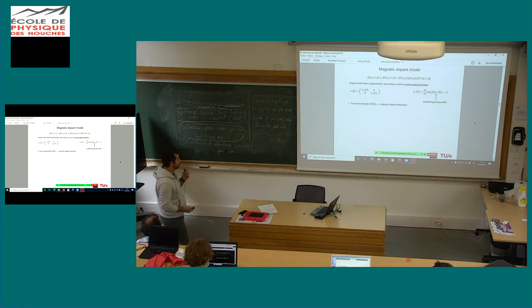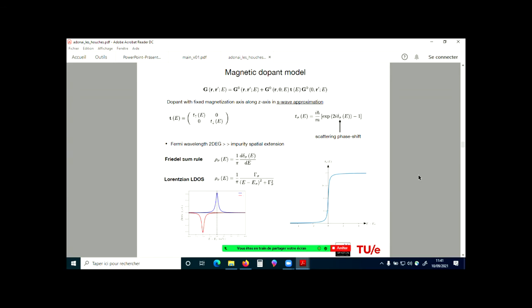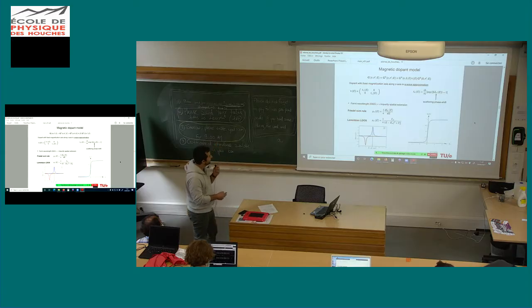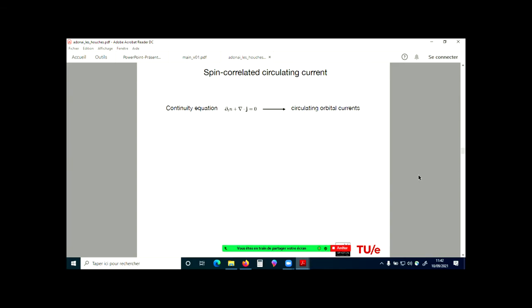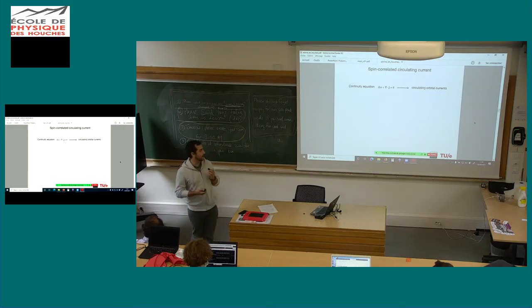I have this expression for the T-matrix in terms of the scattering phase shift. And this can actually be simplified in a simple analytical model as well, using the Friedel sum rule that relates the local density of states with the derivative of the scattering phase shift. So if we model our dopant with a Lorentzian local density of states with some broadening, so sigma corresponds to each spin channel. And if we have, let's say, a fully magnetized state, you can describe it with this model and calculate the energy-dependent phase shift.